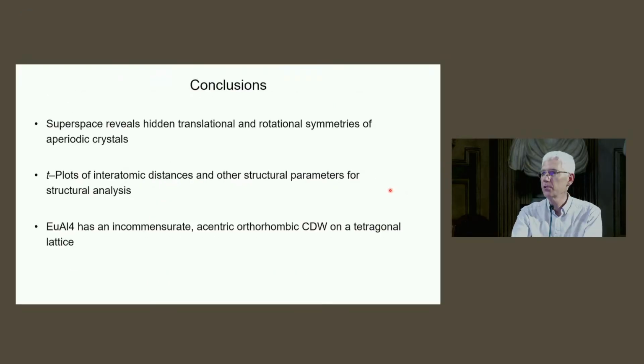And then my conclusions, that the superspace model for incommensurately modulated crystals, but also more general for aperiodic crystals, reveals the hidden translational and rotational symmetries. T-plots can be used to do the crystal chemical analysis by looking at distances, but also angles, magnetic moments, whatever. And for europium aluminum 4 charge density wave, we have found its incommensurate, non-centrosymmetric orthorhombic charge density wave, while the structure remains tetragonal. Thank you.